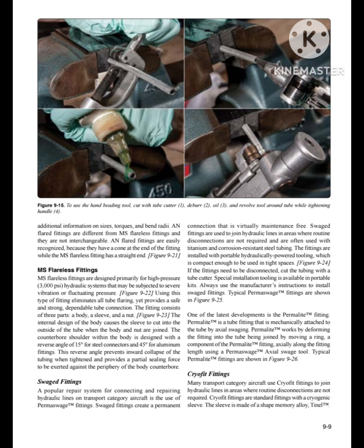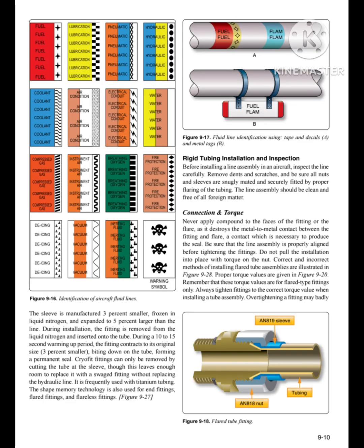Cryofit fittings. Many transport category aircraft use Cryofit fittings to join hydraulic lines in areas where routine disconnections are not required. Cryofit fittings are standard fittings with a cryogenic sleeve, and the sleeve is made of shape memory alloy, Tinel TM. And on the next page, the sleeve is manufactured 3% smaller and frozen in liquid nitrogen.